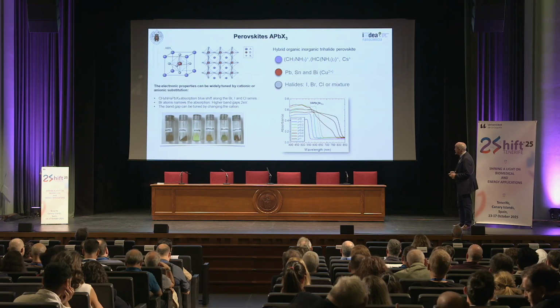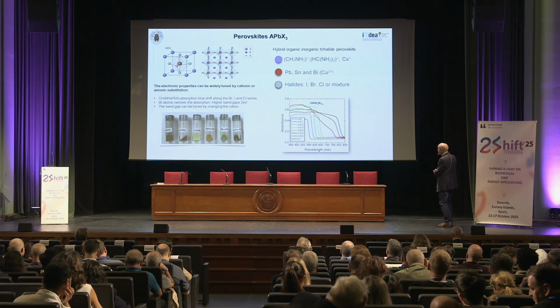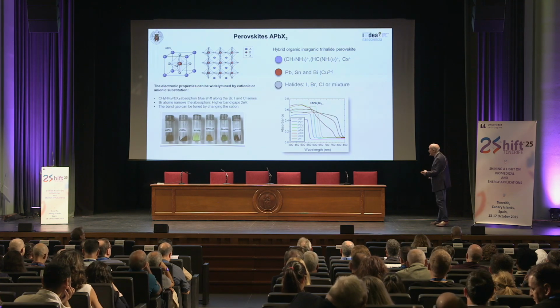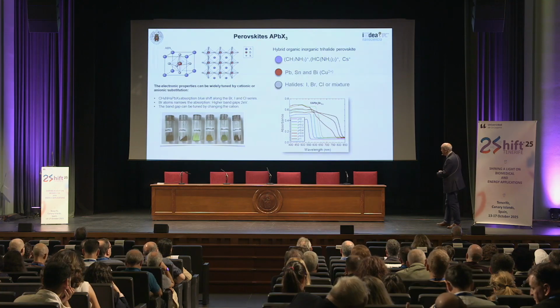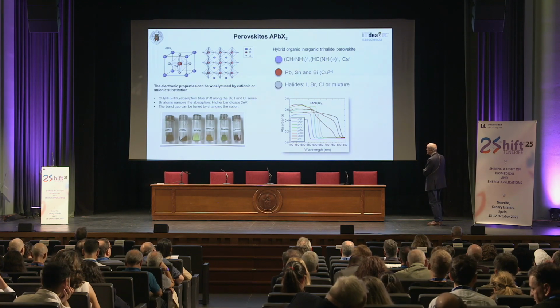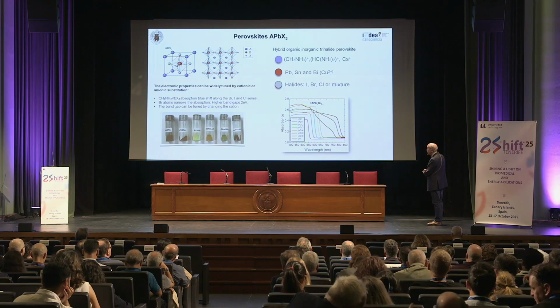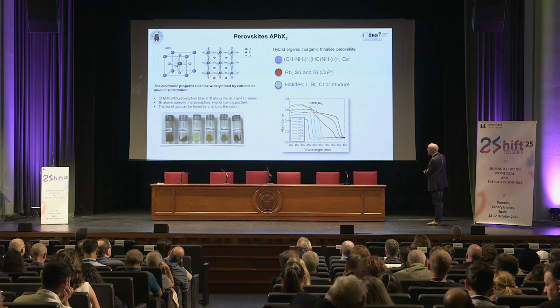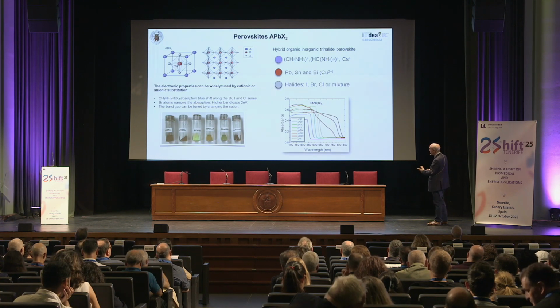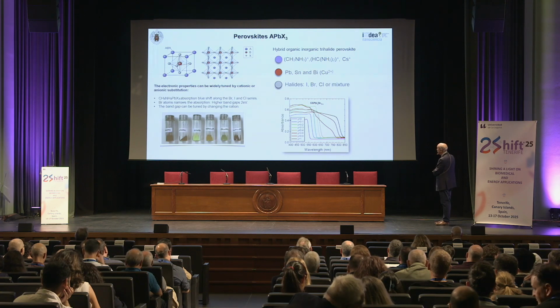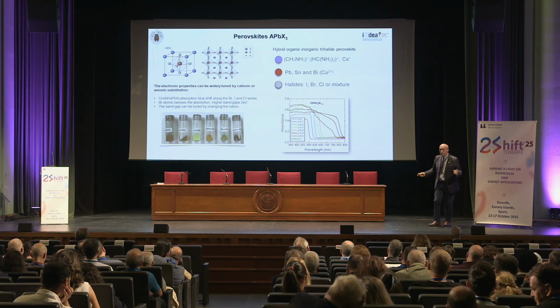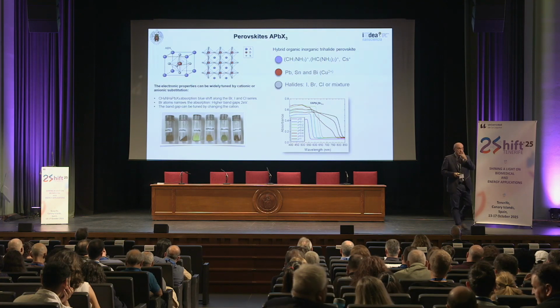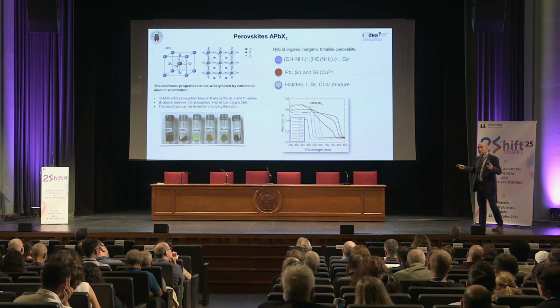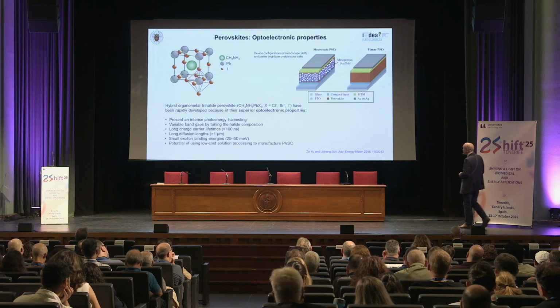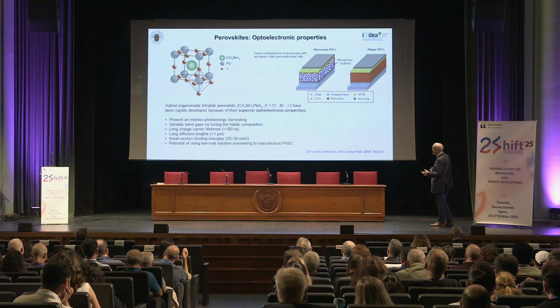And halides, you can use these 3, iodine, bromine, chlorine, or a mixture, which is typically more frequent. So the interest is that if you consider this FAPI, this is formamidinium, lead, and a mixture of iodine and bromine, you can see that when Y is 0, that is only bromine, the absorption is really narrow. However, if you increase the presence of iodine, then the absorption occupies all the visible region. So it is very simple to tune the absorption properties of these materials, as you can see.